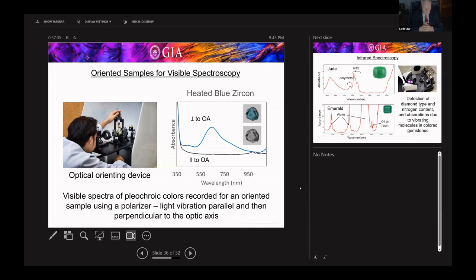And again, when you record the spectrum in the two orientations, parallel and perpendicular to the optic axis, you see the blue and the gray colors. You have to have oriented samples and polarized light to really understand the cause of color in gemstones.